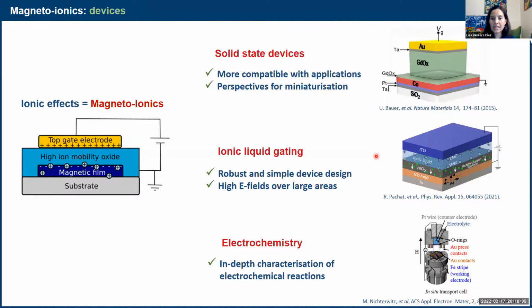So then what happens is that when you apply a voltage, these ions migrate towards the two plates with the opposite charge, and they accumulate there. This can generate a very large electric field, because you apply a voltage and you have the distance between your two plates. But here, the real distance is not the macroscopic distance given by the liquid. It's actually the distance between the first layer of ions that is placed on top of the surface. And this can be very, very small. It's estimated to be an effective distance of 2 nanometers. So if you apply a few volts over 2 nanometers, you get pretty large electric fields.